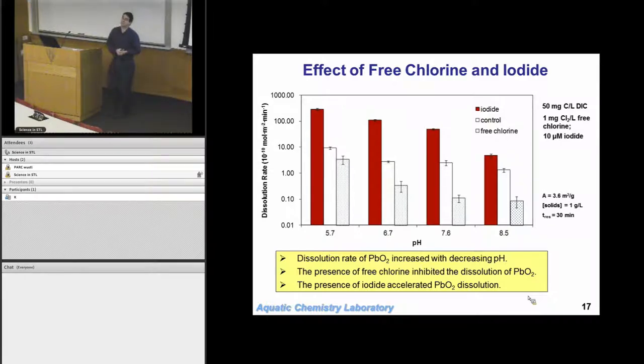It wasn't just that we went from with free chlorine to with monochloramine. If we had natural organic matter, if we had any iodide, if we had any bromide, if we had things in the water, we used iodide in this case as a reductant. If we had things in the water that were a reductant, it actually makes the system even worse. So you're essentially going from with free chlorine on up to with a reductant. And that's what happened in Washington, D.C.